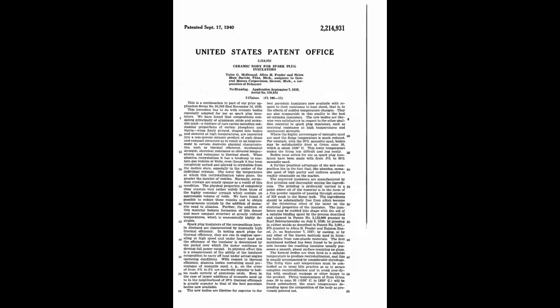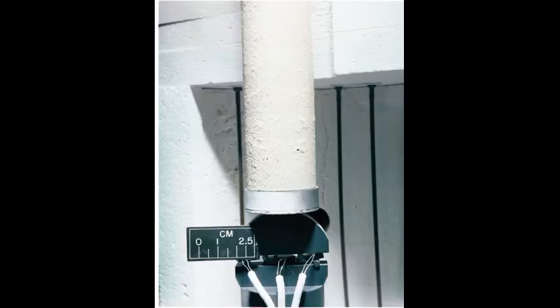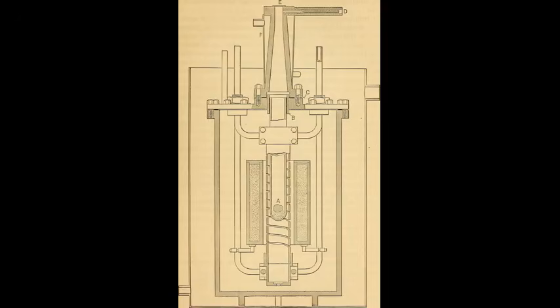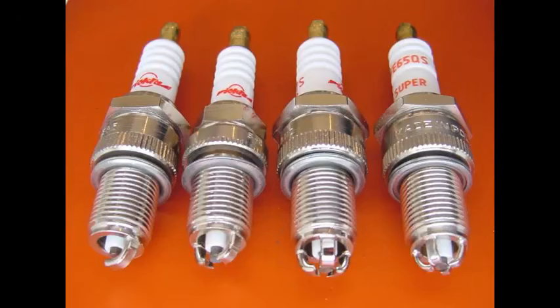Precision machining shaped the unfired blank while it was still soft enough to cut. Carefully controlled firing transformed it into dense ceramic. Diamond grinding finished surfaces after sintering, because hardened alumina quickly wears ordinary cutting tools. The process was not simply a ceramic version of metalworking. Metal can often be machined to final dimensions after it is fully dense. Alumina becomes so hard after firing that extensive machining is slow and expensive. Manufacturers therefore had to produce near final geometry before sintering, predict shrinkage, prevent distortion, and reserve only critical surfaces for diamond finishing.